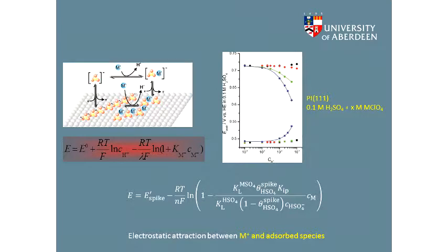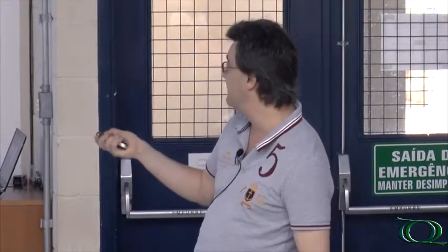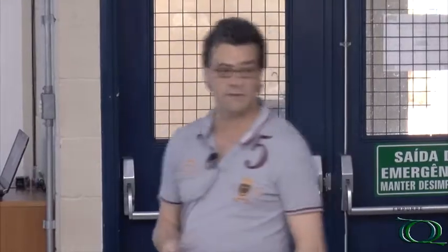I developed again a model. I am not going to get into this because I know that the model needs some correction because it's not perfect yet, but I'm convinced that it works. That's why we have not published it yet, because I still have to make some corrections when I have time. But it's evident that it's the same model which is applying. And we can explain the effect just by the fact that we know that the ordered sulfate structure contains sulfate and water molecules, probably hydronium ions. And when you have cations, these cations are going to replace the hydronium ions and affect the structure of the layer. And that gives an effect which is very similar to what we had with the previous system.